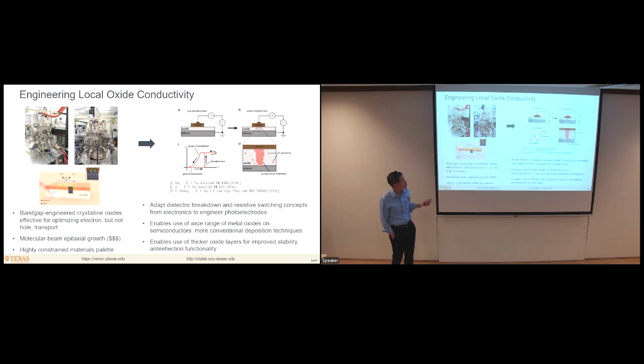We were looking at this for applications like non-volatile memory and neuromorphic computing. But then we realized that this is actually exactly the kind of structure that you want for a photoelectrode as well, because these filaments are good conductors of both electrons and holes. You can have a thick oxide layer on top of silicon, and then the metal can act as a catalyst. This defective region is protected from the aqueous solution by the catalyst on top. So that was the basic idea there.